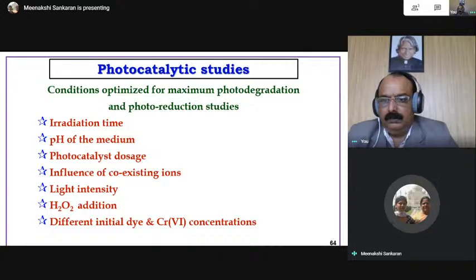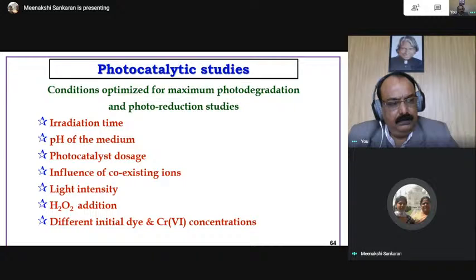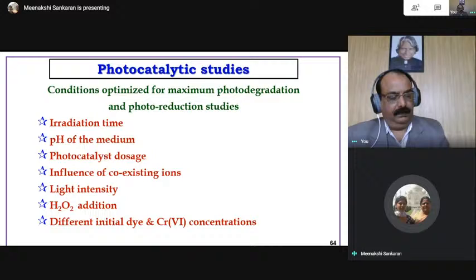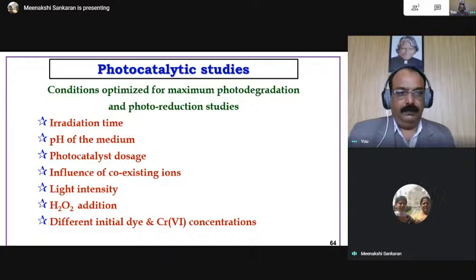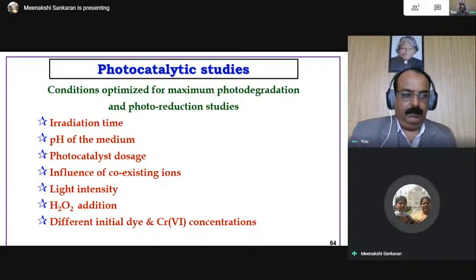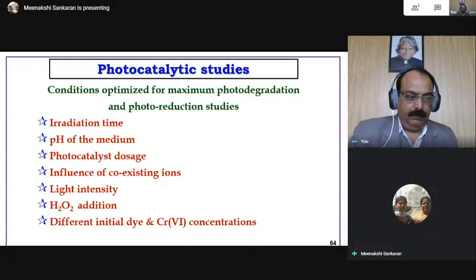For photocatalytic studies, these are all the common scheme. We normally use UV light or visible light for photodegradation studies. So we have to identify the minimum irradiation time, how much time the effluent is irradiated with the UV source or visible source. And I told you pH plays a very important role to make our medium positive or negative. So we have optimized the pH and the dosage of the photocatalyst, influence of coexisting ions, the intensity of light, H2O2, which is used as an oxidizing agent, and different initial dye concentrations.